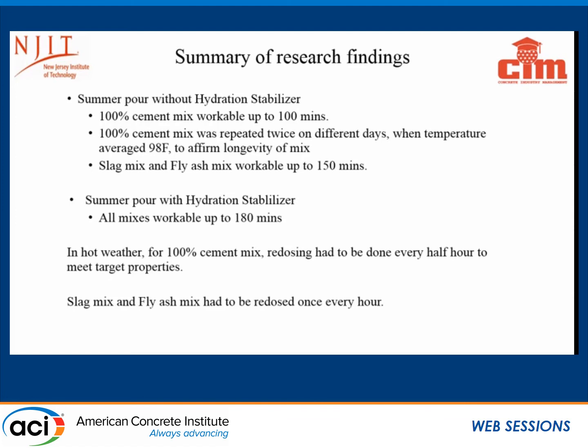So is it safe to assume that if you had a redose, you would have lost slump? Well, the reason for redosing is because of reduction in slump. Yes. So basically, if you had a redose, there's no way you could have made it out to 180 minutes. Correct. So in that case, how can you say then that the hydration stabilizer is working?